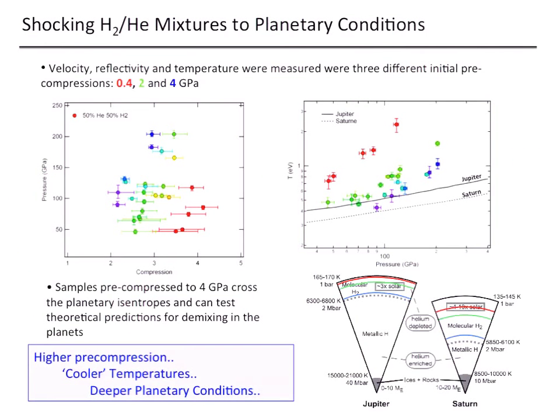Our collaboration looked at a number of different pre-compressions for a 50-50 mixture: 0.4, 2, and 4 GPa. As we change the pre-compression from 0.4 GPa to 4 GPa, we're getting to higher pressures at the same temperature. That's really interesting because it allows us to come over to this part of phase space where we're starting to actually cross the planetary isentropes.